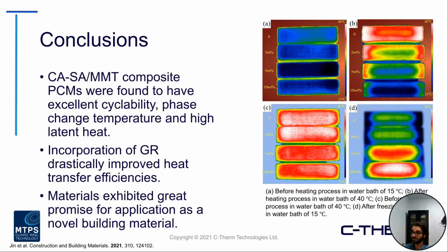In conclusion, they found that the CA-SA-MMT composite PCMs demonstrated excellent cyclability. They did a lot of study on the DSC and various calorimetry properties as well that aren't highlighted here. The phase change temperature was in an ideal range, and they did note the increased, higher latent heat. That latent heat is an important factor when you're considering thermal management applications, or heat storage, I should say, within the building envelope if you were to incorporate these.